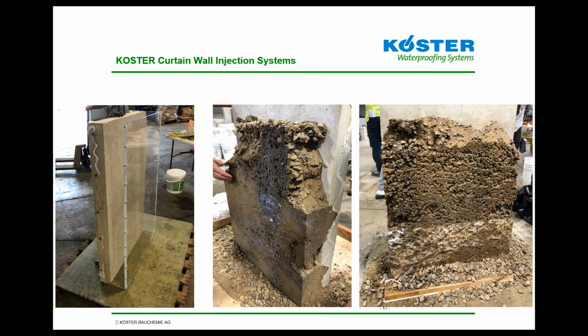Again, what we're looking for here is, we have some more pictures later on of what we've discussed, those grout balls, those circular shapes which can be formed by the injection material as it's injected. In the real world, though, this injection material, especially since it is low viscosity, is going to behave as water will and follow any path of least resistance, filling voids along the way. So we don't always get those ideal, perfect grout balls. But as you can see here, we've pulled the plexiglass back. We have a solid wall where the material has consolidated any voids and reacted and given us that barrier that we're looking for of that waterproofing material.